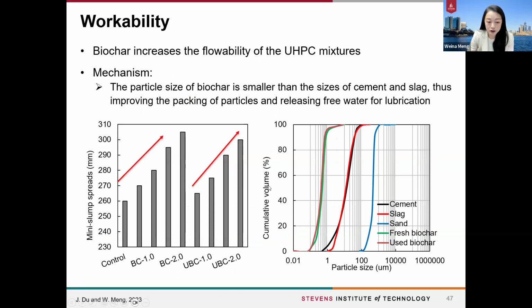So both the biochars improved workability. And the reason is that the biochar has smaller sizes compared to the cement and slag, and they improve the particle packing density and release more free water for lubricating the particles.